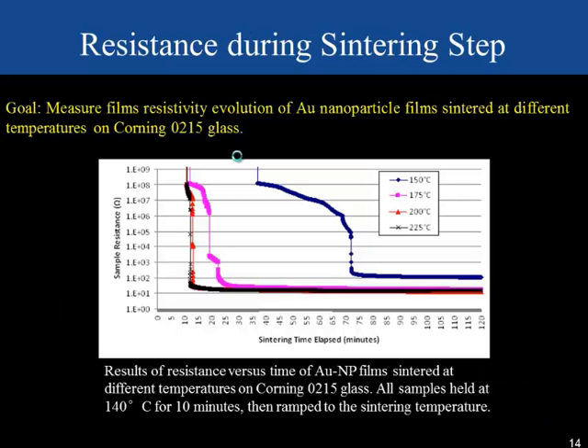As I mentioned earlier, during sintering, a large resistance drop can be observed. And just to show our test setup in action with that part of the process, these are 4 different films that were deposited in the same way. For the first 10 minutes, they're left at a low temperature to evaporate their solvents. At the 10-minute mark, the temperatures were increased, as shown here. After some time, a large decrease in resistance is observed as the organics break down and the nanoparticles begin to connect with one another and sinter together and conduct. After some period of time, the resistivity of these films becomes more stable, and we have a stable gold film, ideally.